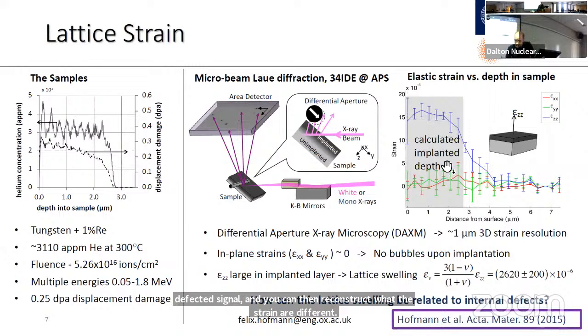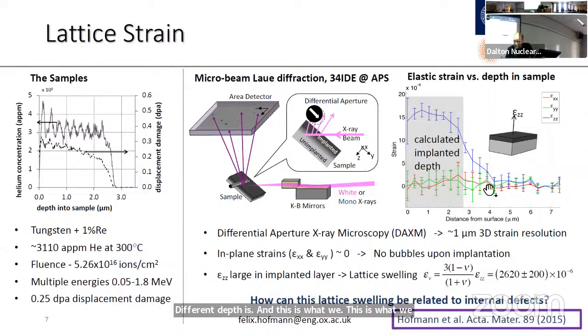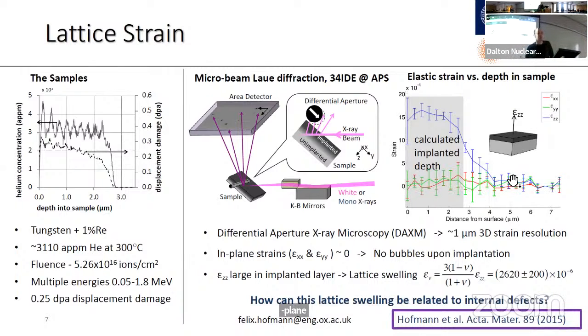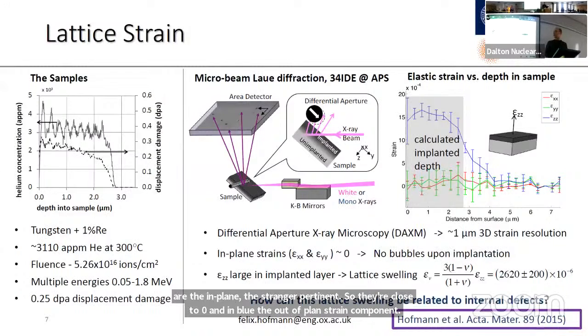And this is what we measured. So this here is now the distance from the sample surface. This here is strain. In green and in red are the in-plane strain components, so they're close to zero. And in blue, it's the out-of-plane strain component. You can see that this helium implantation has resulted in a huge amount of lattice swelling.